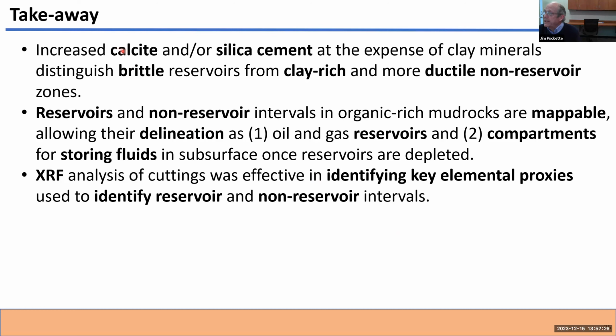So when we see increased calcium or increased silicon at the expense of clay minerals, that's good news. It makes the rock more brittle. And the great thing about it is, if we have adequate well control, and you're in an area where they drilled through some of these organic rich mud rocks to get to deeper Silurian, Devonian, or Simpson group, Hunton, Simpson group areas in Oklahoma, may apply to different intervals in other basins, but using resistivity, if we don't have the other curves, but certainly resistivity with gamma ray, you can map these subunits, and where we have adequate well data, we've successfully mapped them.